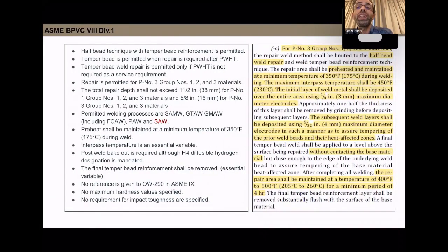In ASME Section 8, only half bead is allowed. The permitted materials are P number 1 and P number 3 group 1, 2 and 3. And the permitted welding processes are SMAW, GTAW, GMAW, including FCAW, PAW, and SAW. Although SAW is one of the accepted methods in ASME Section 9, it is only acceptable in ASME Section 8 Division 1. So they have a preheat requirement of 175. Interpass is an essential variable here, and post-weld bake out is also required. The final temper bead reinforcement shall be removed. It is an essential variable here.